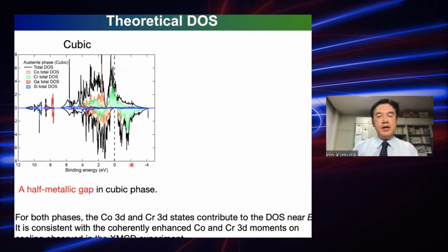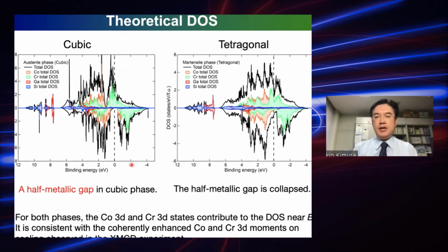So now let me show you the first principles calculation, the theoretical density of states, in the cubic phase and also in the tetragonal phase. As you can see, in the cubic phase, you see the minority spin gap, which shows a half metallic band structure. In the tetragonal phase, you see that this half metallic gap in the minority spin is collapsed.